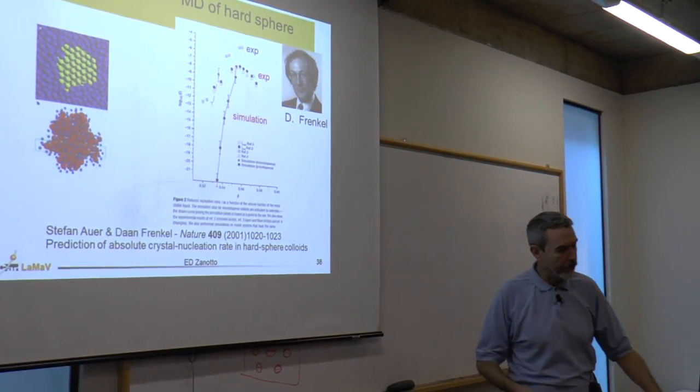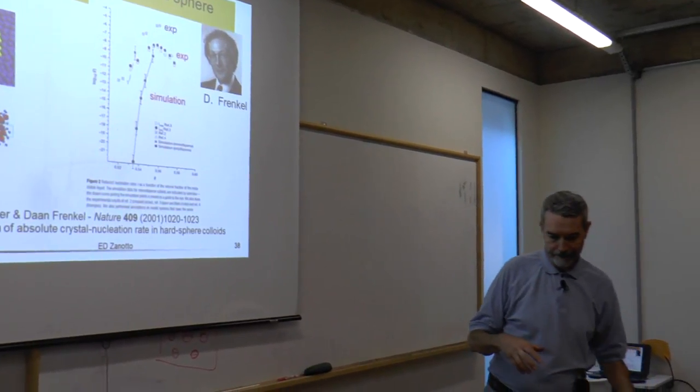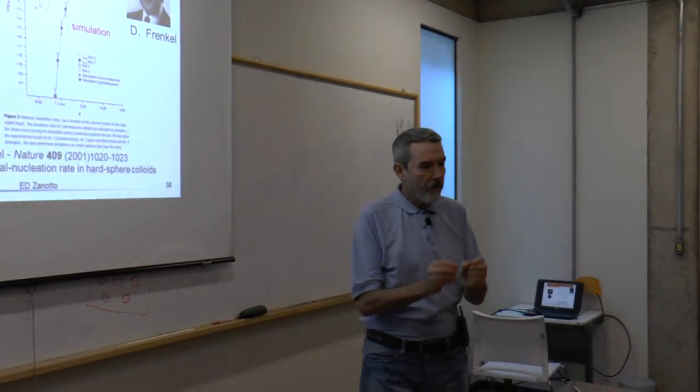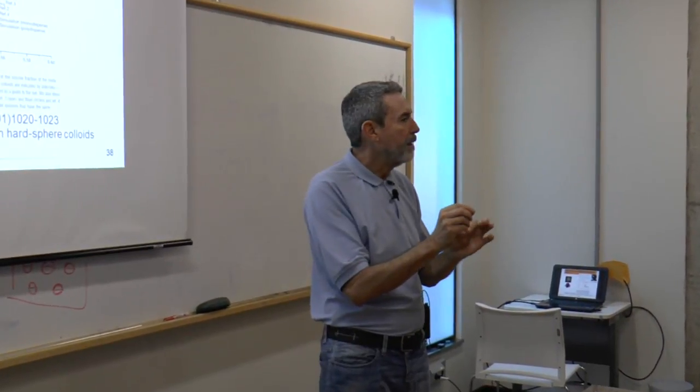This is really interesting. This is not a conventional glass. If you have colloidal particles, of about 1 micron in size, 2 microns, half a micron or so, dispersed in a liquid, you can produce a colloid, and then, rather than changing the temperature, you start to take out the liquid with a syringe.